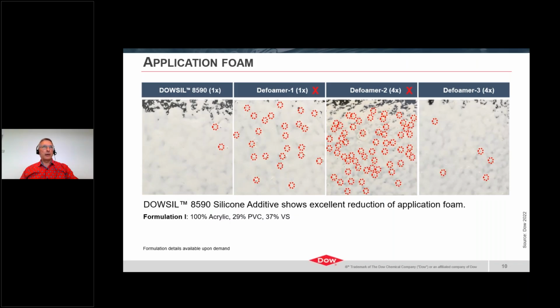In this case, after drying in controlled conditions, the films were analyzed by automated image analysis, which identified each individual bubble formed in the coating due to bubbles trapped in the final film. And these bubbles are indicated by the red circle on the images. As we can see, there are significant differences and variation in the ability of the tested defoamers to control the appearance of these defects.